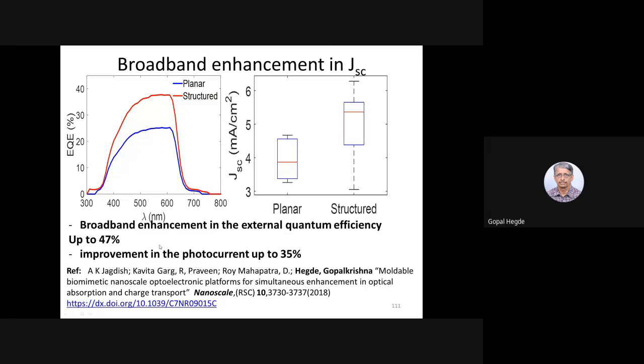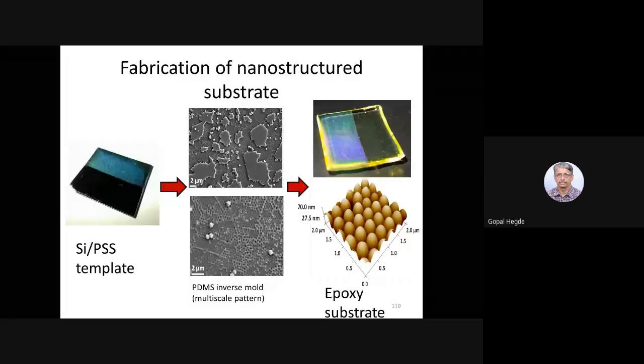So what we observed was an improvement in the photocurrent up to 35%, enhancement in quantum efficiency is 47%, and overall we saw an increase of about 40% in efficiency by introducing nanostructure in a photovoltaic device. I think this was published in 2018 in Nanoscale. I think we are working on large scale production. We are trying to develop, along with Bharat Electronics Limited, large area solar cells. Okay, this is where the real nanophotonic application is.